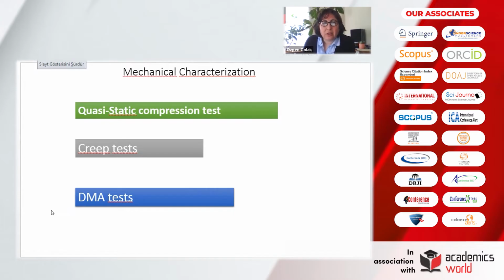So following the manufacturing process, we have done mechanical characterization, and we start with the DMA, dynamic mechanical analysis, quasi-static compression test, and creep tests are performed. In the quasi-static compression test, we perform the experiments at different strain rates because graphene-epoxy or polymer matrix composites are rate dependent. So we wanted to investigate the rate dependency. And creep experiments are quite important. So that's why we performed some creep experiment at different stress levels, and the DMA also another test that we have performed.